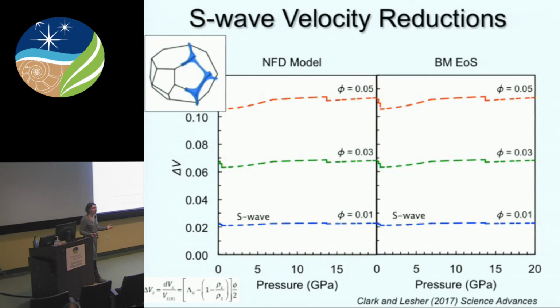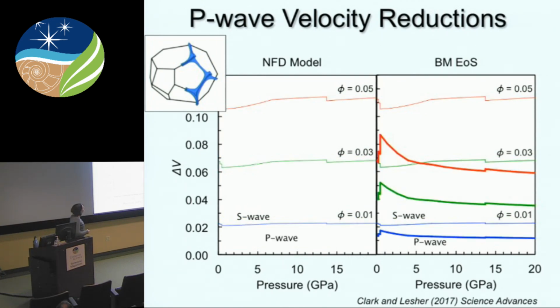And this has to do with the fact that shear waves aren't supported, right? So we don't really have a parameter that's dependent on the P-wave velocities of melt in the equation that actually gives us our velocity reduction. So here we have different melt fractions, 1, 3, and 5%. And what you can see, again, perhaps not surprisingly, is that as we increase melt fraction, we get an increase in the velocity reduction. Okay, so now let's look at what happens for our predicted P-wave velocity reductions.